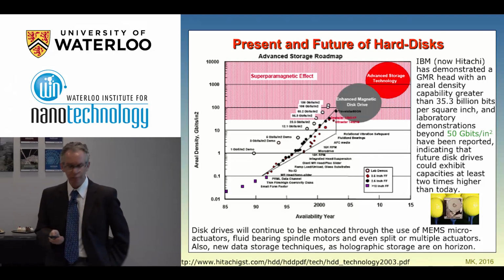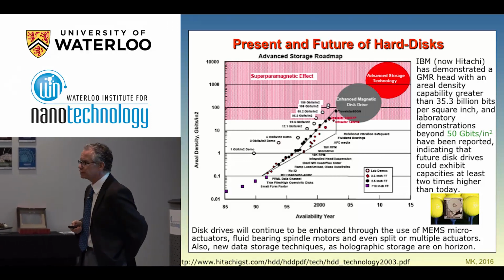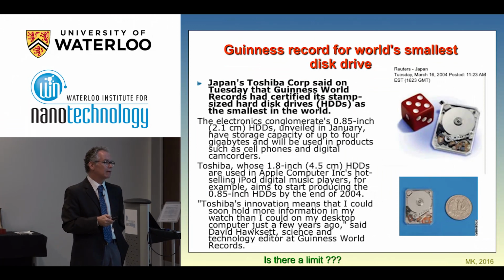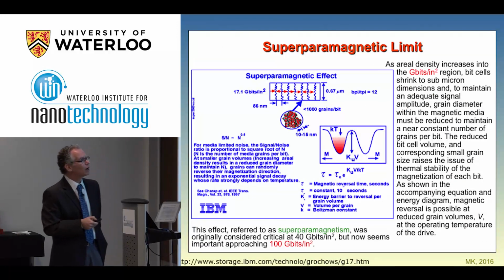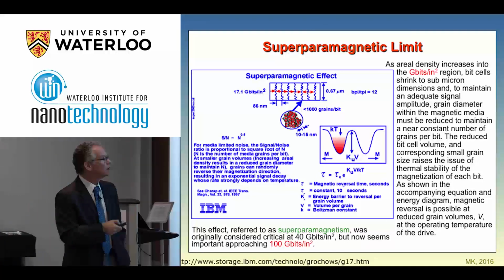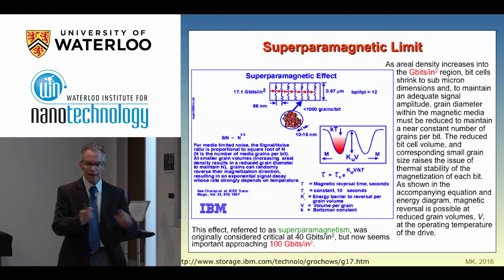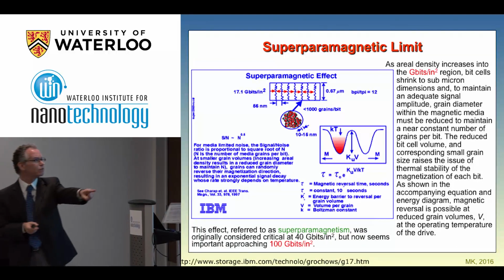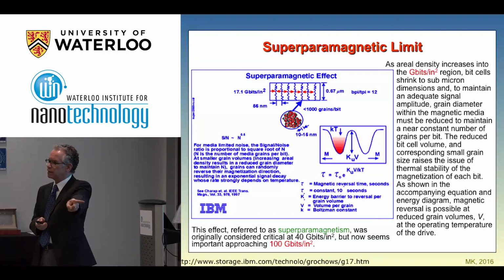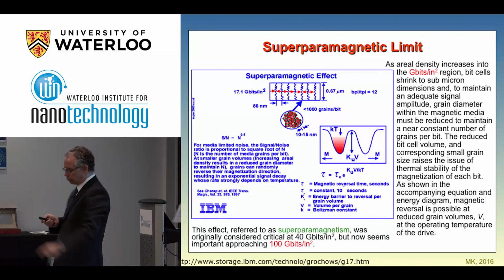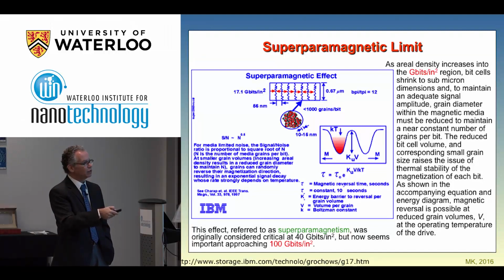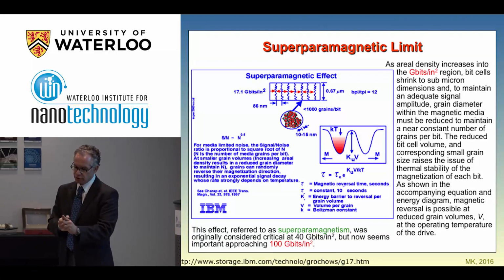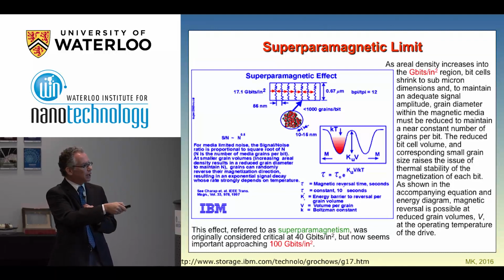We have the so-called superparamagnetic limit of these bits. I will try to explain a little bit more about what we mean by superparamagnetic limit. Whenever you have a magnetic region, you have a magnetic moment, and this magnetic moment points toward one direction, as I explained, 0, or the other direction, which is 1. Both directions are, let's say, a minimum in this energy landscape here. So you have a minimum here and a minimum there. And in order to go from one to another, of course, you can apply a magnetic field that makes this barrier change, and then you can change the position.